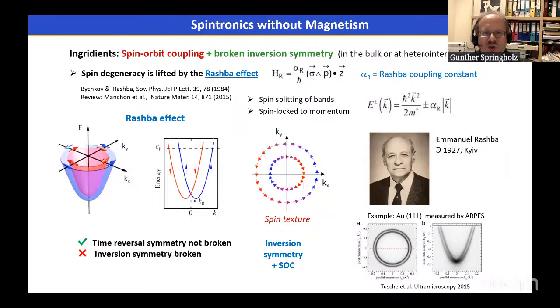Some different topic, and that is spintronics without magnetism. And the ingredients are that one needs material with strong spin-orbit coupling as well as broken inversion symmetry. And this broken inversion symmetry can either arise from the missing inversion or the inversion asymmetry of the bulk crystal lattice, or structural inversion symmetry, as for instance occurs at hetero interfaces between two materials or in systems where there is a band bending towards the surface.